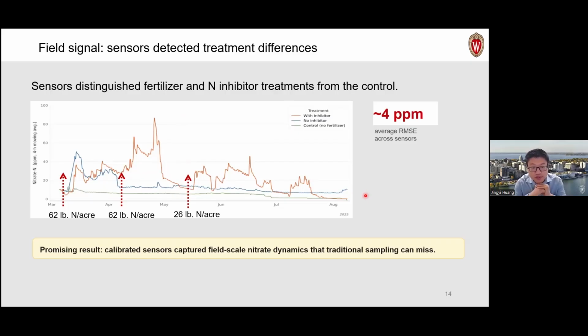So based on this preliminary result, we can see that our sensor, only after you calibrate it with the real soil samples, captures the spatial variability of the soil nitrate due to the different treatments, but also the dynamics following the addition of nitrogen fertilizer events. We also compare our nitrogen measurement from the sensor with the soil sample readings. That gives us an error of our sensor of roughly 4 ppm.